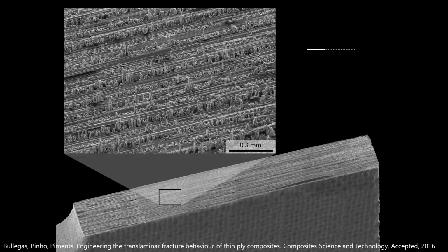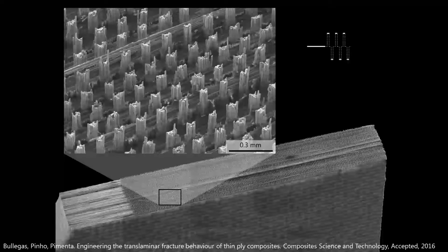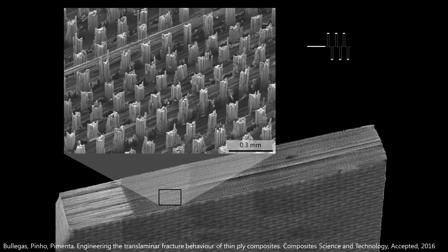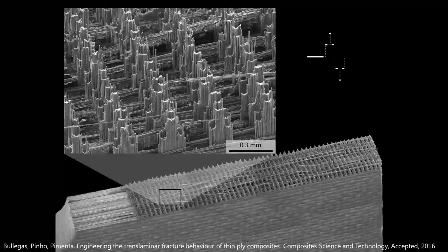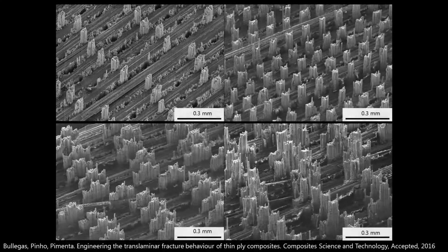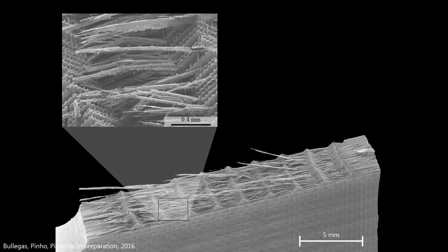By comparison, now using exactly the same scale, this is the type of materials we were able to design first and produce next. These are materials in which the fracture surface is the result of the microstructure that we engineered into the material, and now you have much larger pullouts that dissipate more energy. We can do this with one scale. With 2 scales, we can create at this stage whatever patterns we want to create, and we can even, if we were so inclined, create a microstructure such that when you break the material, it spells Simulia or Dassault Systèmes on it. The last microstructure we created is this one. We called it a shark teeth microstructure because it has these teeth that look like shark teeth.